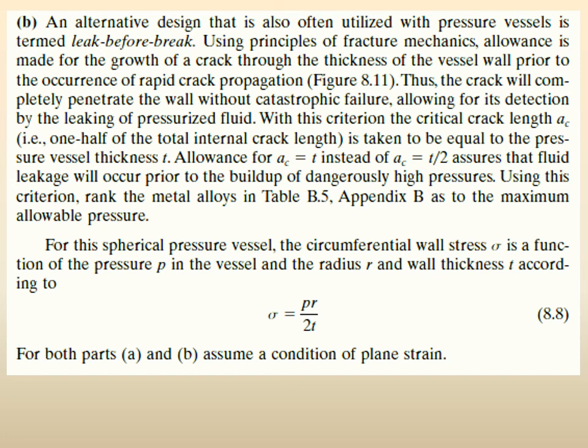And as soon as a through thickness crack is there, the hole in the wall is there, then whatever extra pressure is there will be released, right? It is now a leak. So now the whole pressure vessel will not crack, will not burst, will not fracture. Only once the crack goes through the thickness, then it is a through thickness crack, and that means that now it can start to leak. So this is the other approach, right? The first approach is yield before failure, and the second approach is leak before failure, right? And using this approach you solve. So we will continue with this.